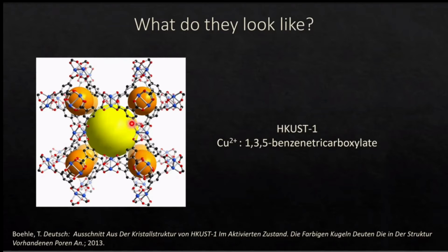Whenever that expands in 3 dimensions, we end up with this really unique porous structure where we have a large pore represented by this yellow ball, and then smaller pores represented by these orange balls. Inside of those, you can catalyze chemical reactions, you can trap gases, you can do all kinds of things. This structure in particular has been shown to catalyze the reduction of carbon dioxide, like we were discussing earlier. But this is a copper 2+ MOF, so we're actually going to be discussing copper 1+ MOFs, specifically copper iodide.